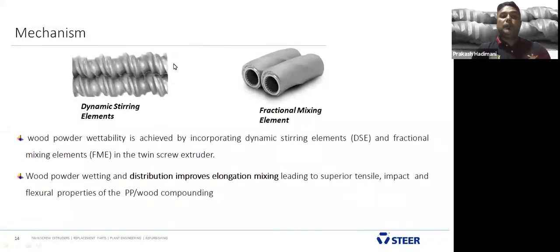What's the mechanism of dynamic stirring elements and fractional mixing elements? When we have wood powder, it has to wet in the polymer matrix, achieved due to the stirring effect. It reduces the melt temperature and also gives a uniform shear rate throughout the system. It also distributes the polymer and wood composite and increases the elongational flow by using fractional mixing elements, and also improves tensile and impact strength.